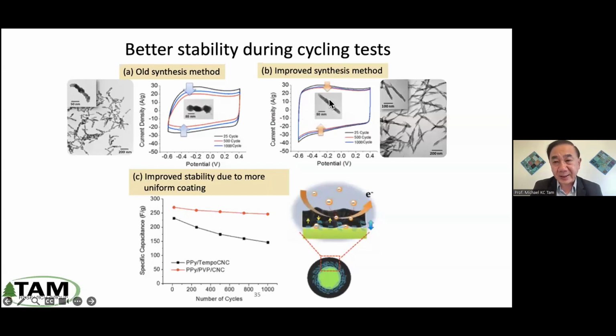Then on the right is this new coated system. You see that you get very uniform coating, and that results in a capacitance drop of only 5%, high capacitance and a drop of 5%. So interface is very, very critical in regards to making material that's stable for, in this case, charge storage.